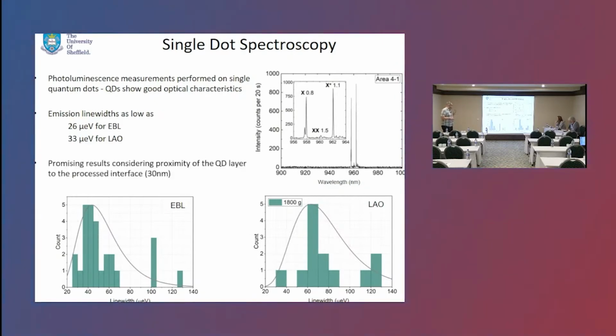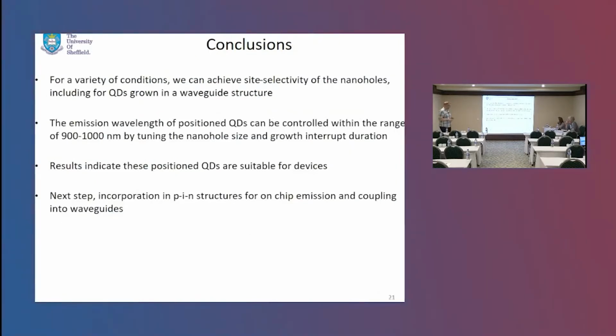So this is promising. It shows that, remembering that we have a growth interface, which is 30 nanometers away from the dot layer, that we're still getting very good optical properties from these, and we want to push them further, and there's various different ways that we could do that. So, said it was short.